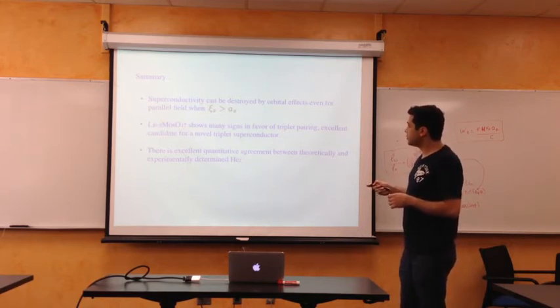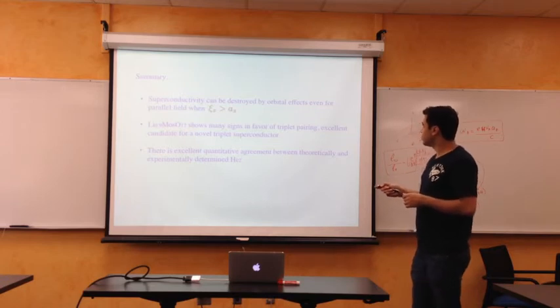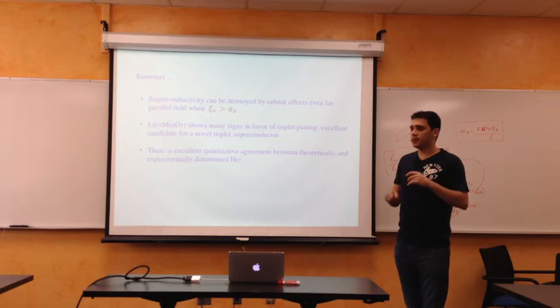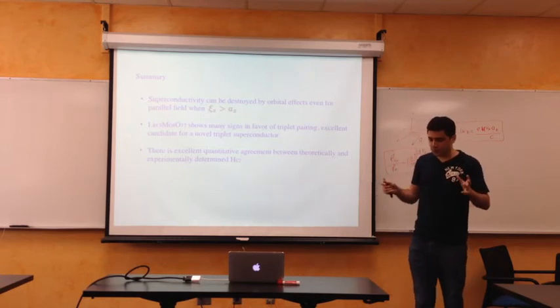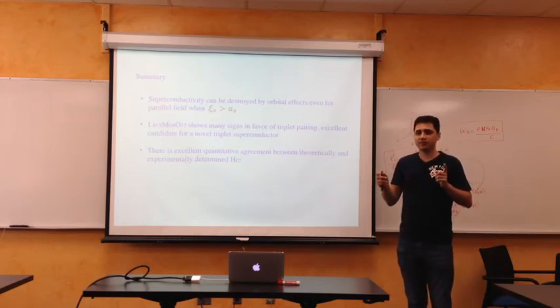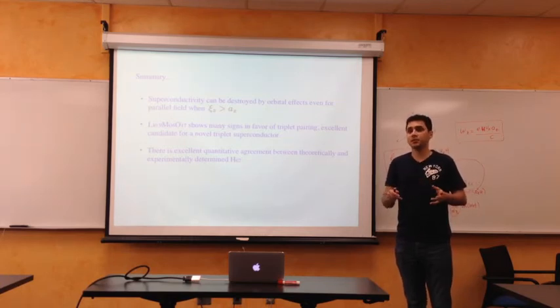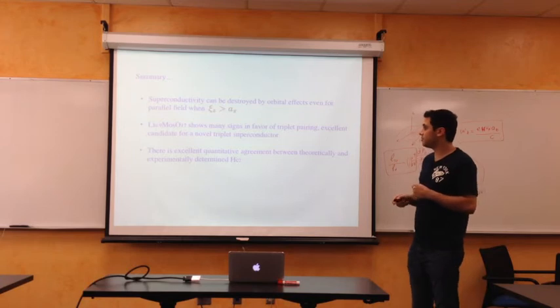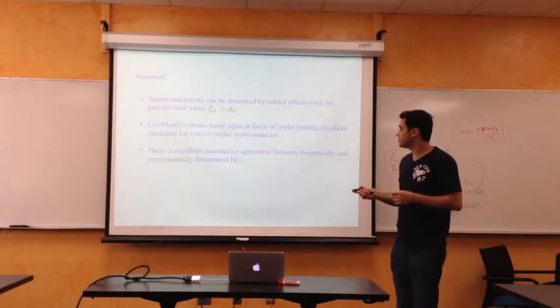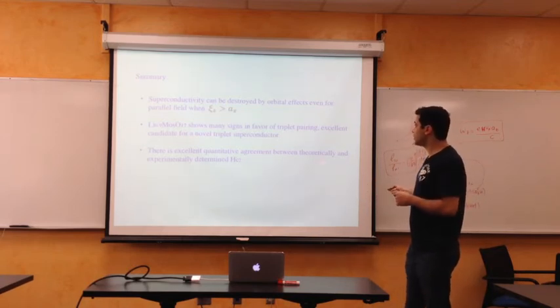Purple bronze, lithium molybdenum oxide, shows many signs in favor of triplet pairing, and it would take an extraordinary coincidence of factors to suppress Zeeman splitting enough to account for such a high magnetic field, which we don't think is possible.